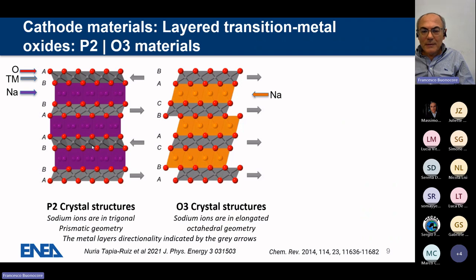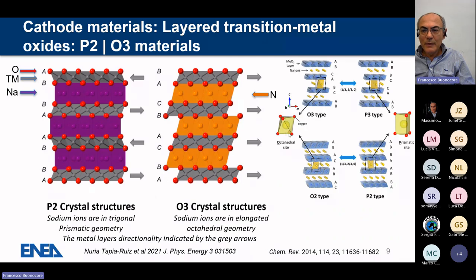Here I show two typical crystal structures: the prismatic P2 symmetry and the octahedral O3 symmetry. The numbers 2 and 3 refer to the number of layers present in the unit cell. So for a prismatic P2 crystal, there are just 2 layers per unit cell. They are prismatic or octahedral depending on where the sodium is located. It can be in the octahedral site, in the O symmetry, or in the prismatic site.